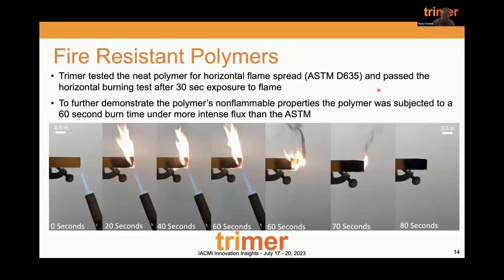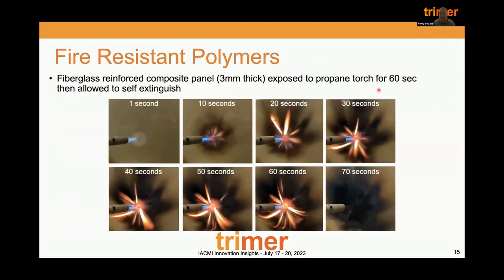I'm going to go through this a little quick here, but show you some data on fire resistance. This is not an ASTM standard. This is just a neat polymer being subjected to a blowtorch. It'll exhibit some small amount of flame, but no sagging, no flame spread, and it self-extinguishes very quickly. You do the same kind of test on a composite. This immediately extinguishes itself. This is a 3 millimeter thick panel. Didn't have any darkening or anything on the backside.